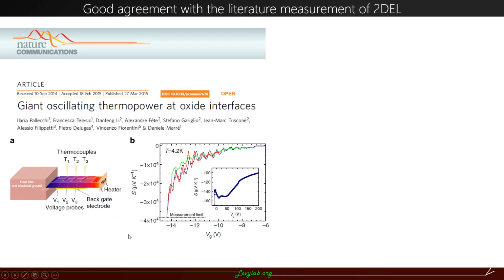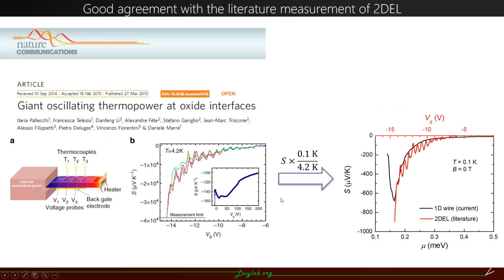We also compare our results with the one published in the literature, who measured the thermal power of the 2D electron gas at this interface at a temperature of 4.2 Kelvin. Assuming linear temperature dependence, we convert the results and compare with ours, and they compare quite well, which confirms that our measurements could be correct.